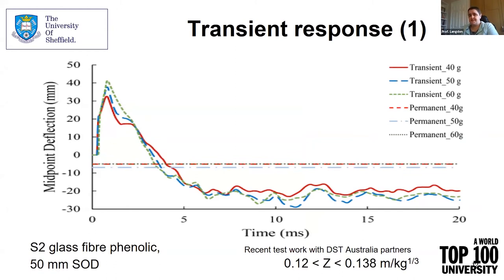So this is that S2 glass fiber phenolic panel that I showed you a few moments ago, loaded at three different charge masses, 40, 50, and 60 grams. We did this work in collaboration with our DST Australia partners. And hopefully what you can see here is three colored lines, red, blue, and green. Those are the transient responses. They peak between 30 and 40 millimeters in the direction in which the blast is moving.